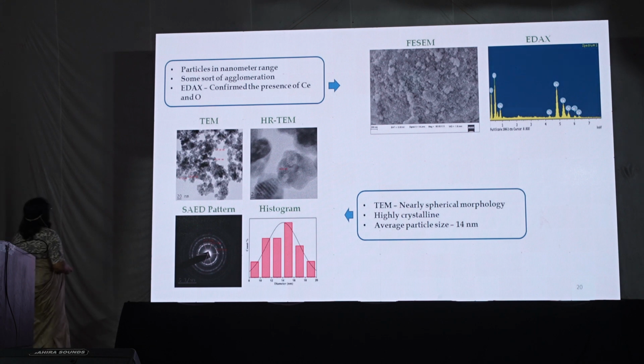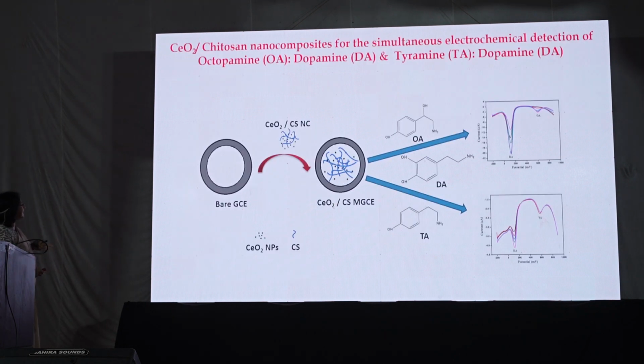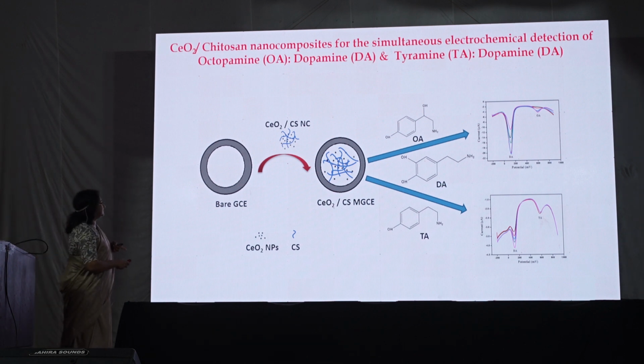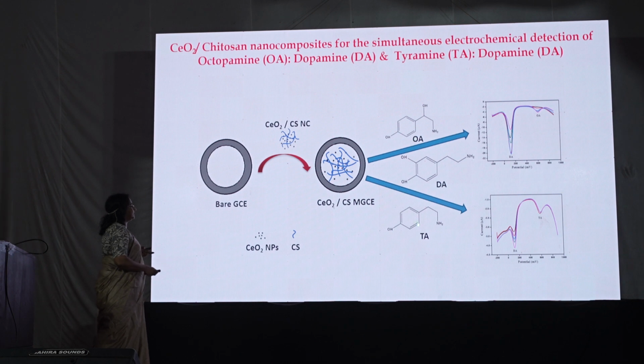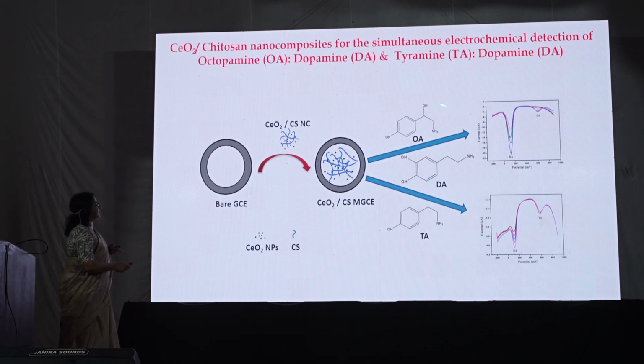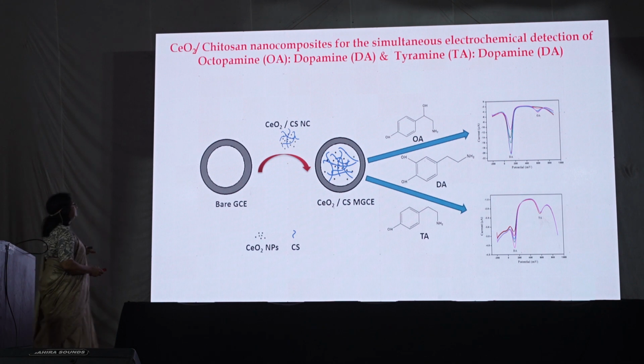Here the particles were synthesized in the nanometer range and some agglomeration was there. SEM EDAX confirmed the presence of cerium and oxygen, and the particles are spherical in morphology and highly crystalline, with an average particle size of 14 nanometer. The cerium dioxide nanoparticles were modified on a bare glassy carbon electrode, which was further used for the detection of dopamine, octopamine and tyramine. Octopamine and tyramine we have used to study interference.